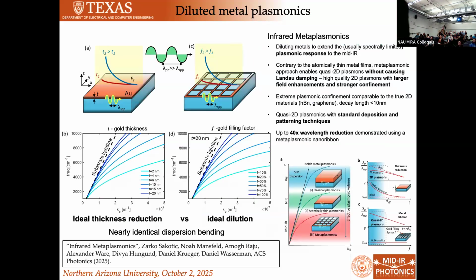But then we started thinking, well, we might be able to actually approximate atomically thin metal films doing this. So instead of having an atomically thin metal, we can just take our metal and perforate it in such a way that we just take away all of those free carriers. Now, this only works if you can do this on a length scale that's smaller than the wavelength of your light. Because otherwise you'll get diffraction and all sorts of other effects. So this is what your dispersion looks like when you change the gold thickness down to 2 nanometers. And this is what happens when you essentially reduce the fill factor of your metal. Right? And if I didn't have the legends here, you wouldn't be able to tell the difference. From the point of view of light, it can't tell whether you've made it thin or you've just chopped out chunks of a thicker layer.